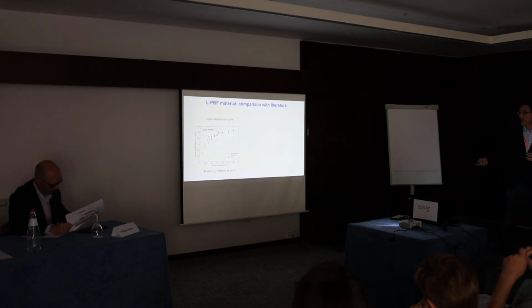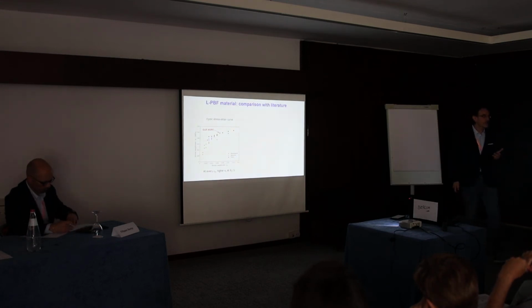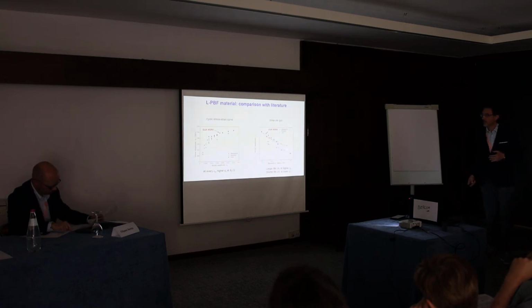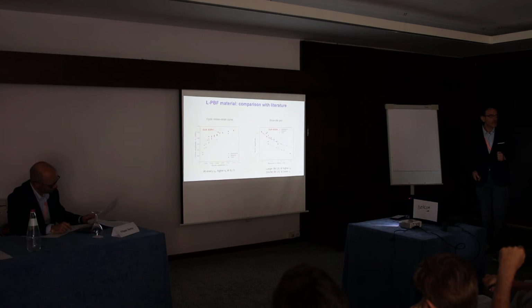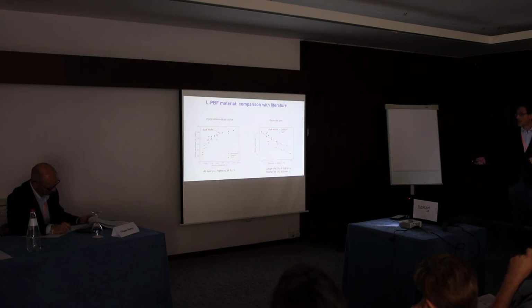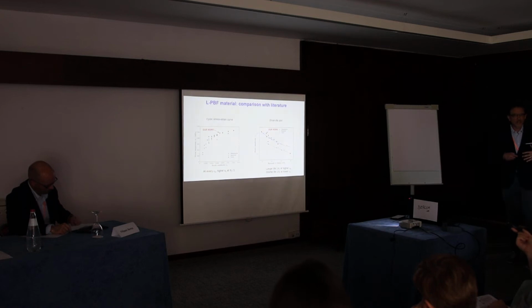And here is an example of comparison concerning the cyclic stress-strain curve. The red points here are the experimental results from our work, and you can see that there is a good correlation with literature data, although our points seem to be placed in the top part of this figure. And then we also compare the fatigue life data of our work with literature data. Again, here you can see that there is a pretty good correlation of our data with literature data, apart from the data from Shrestha and others that show a much shorter fatigue life. And this seems to be caused by much larger lack of fusion defects as documented in the article.